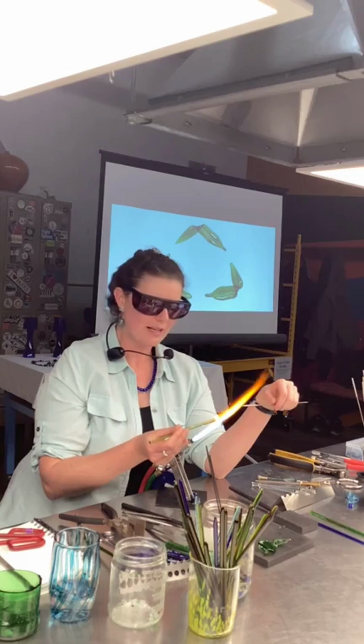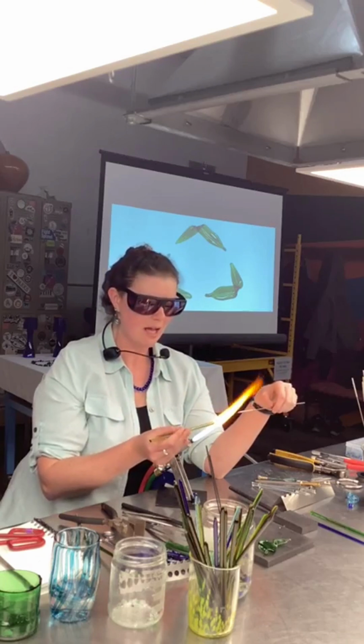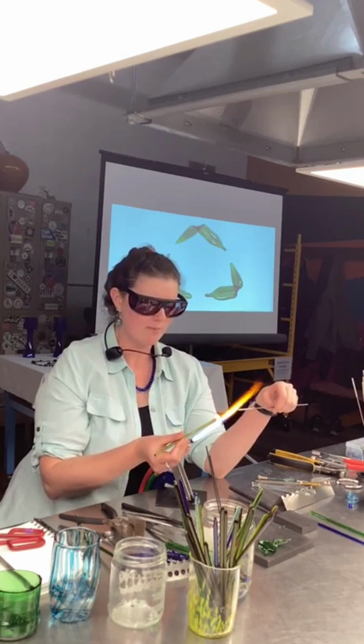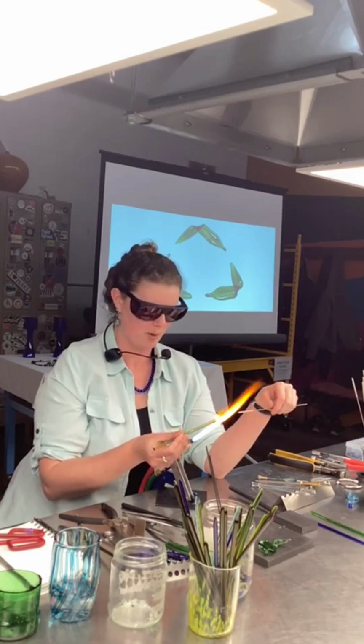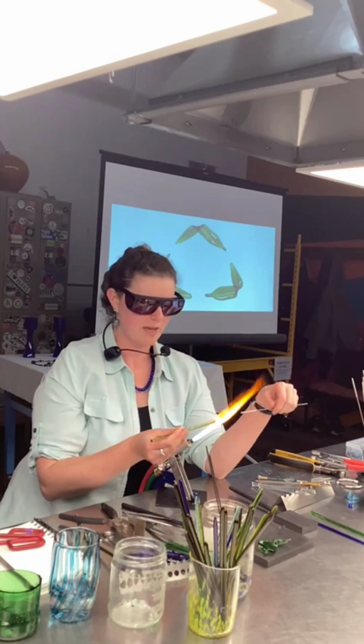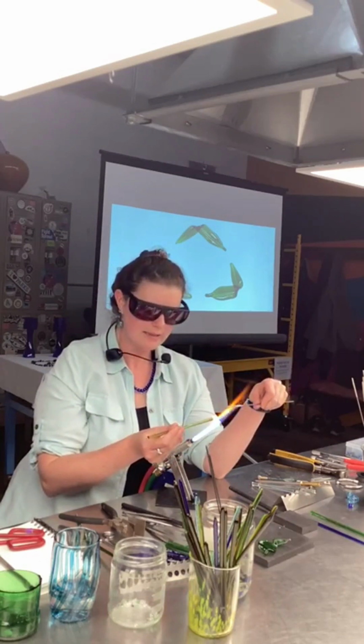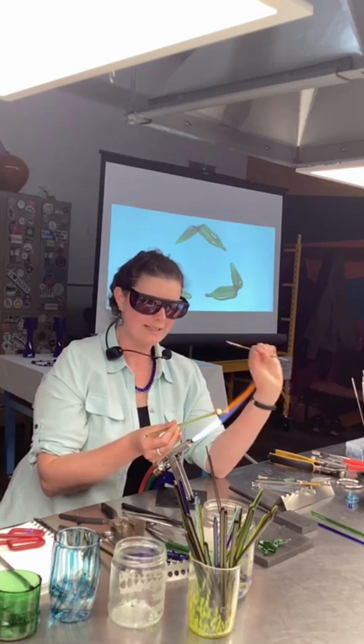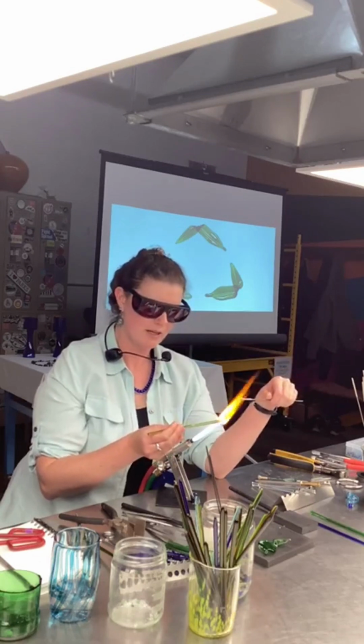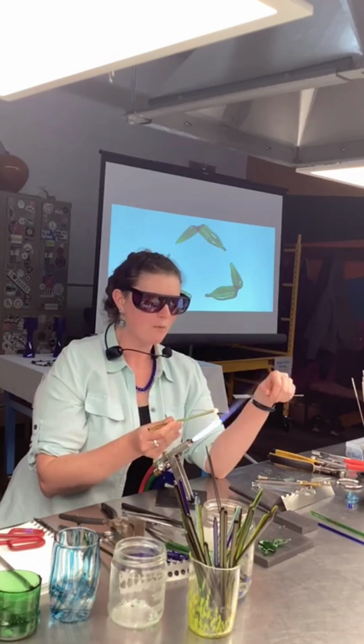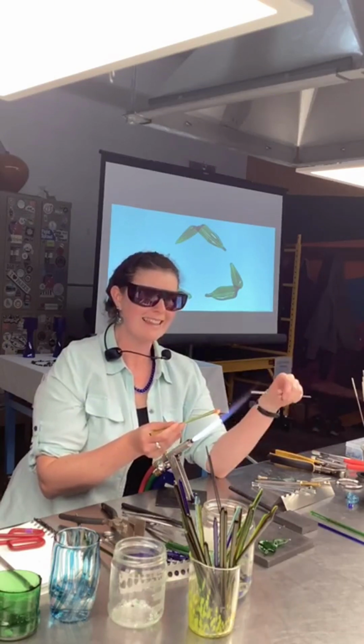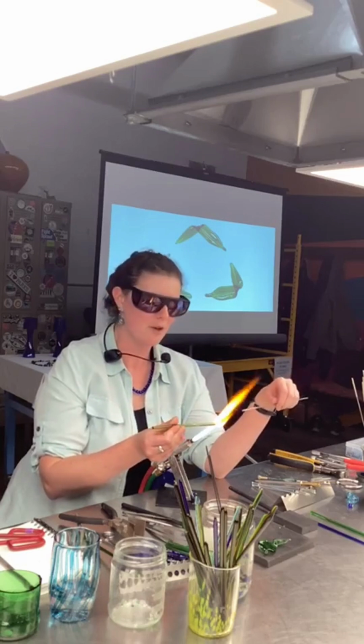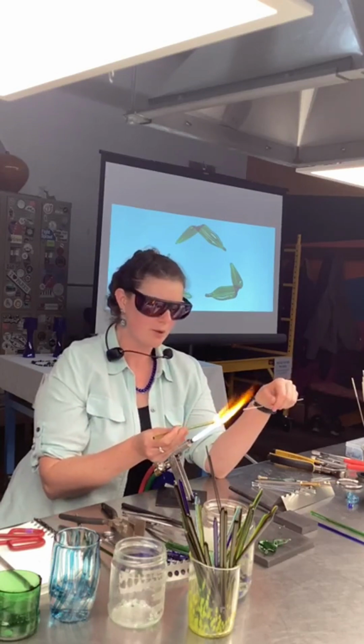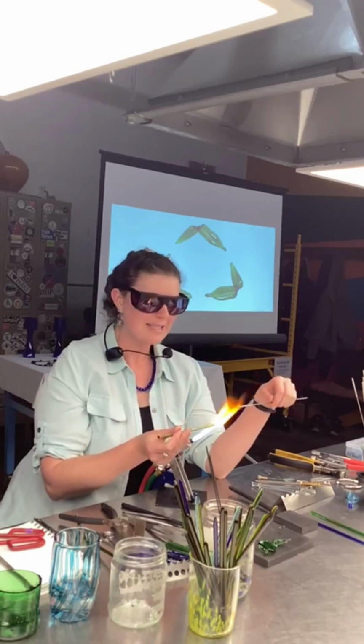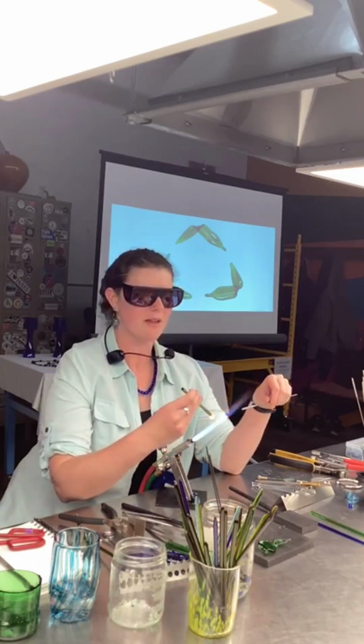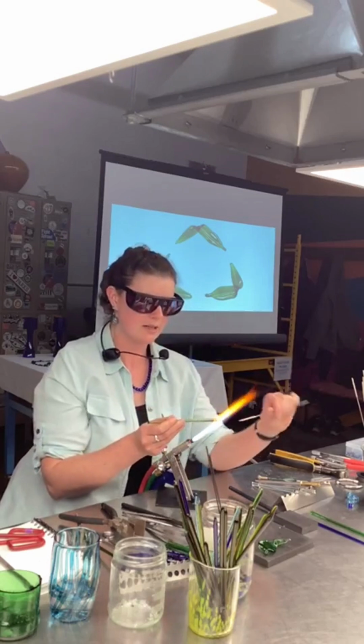And the science doesn't really support that anymore. One, glass was such a rare commodity that having a liquid pool of it was almost inconceivable. And so instead, what we are starting to develop the idea of is that they had powdered glass, and that they were heating up the core on some kind of mandrel, even if the mandrel wasn't metal yet. It was probably a ceramic mandrel. And then rolling the hot core in powdered glass in layers to build up the thickness of the walls of the core-formed vessels. And the reason for so long we thought that it was done by dipping those core forms is because we came to it from an extremely hot shop centrist viewpoint.